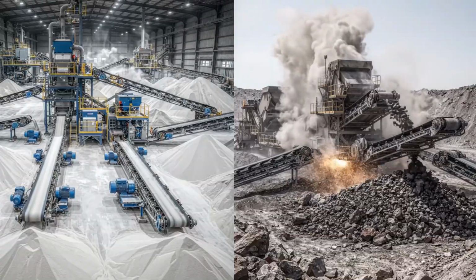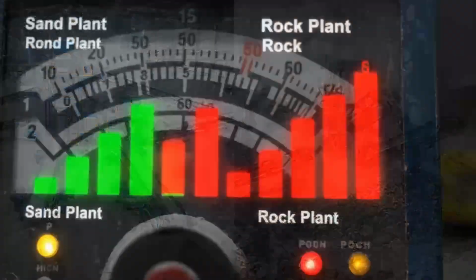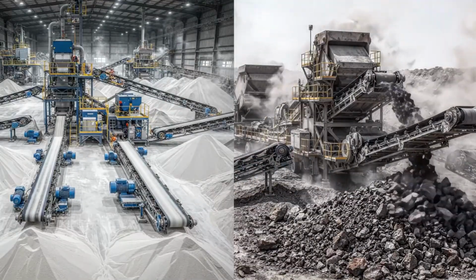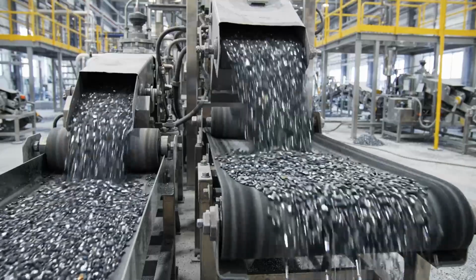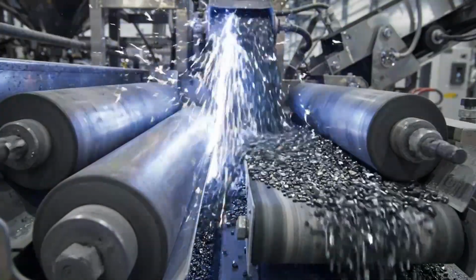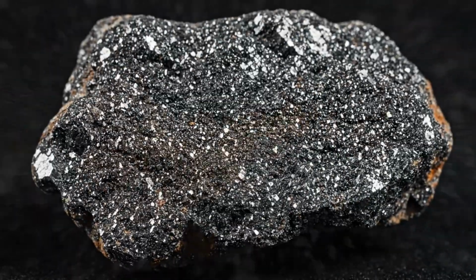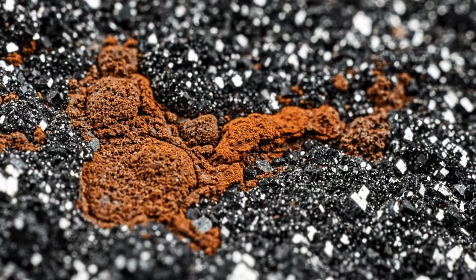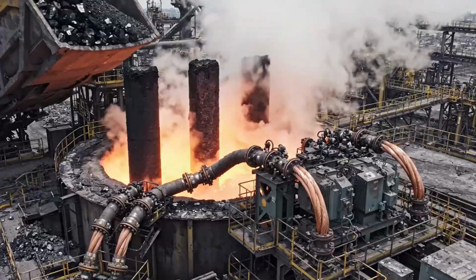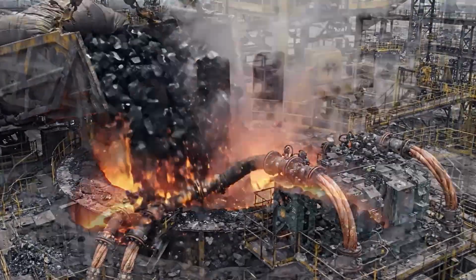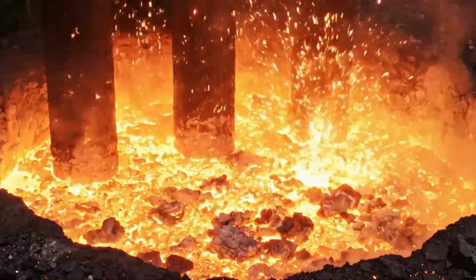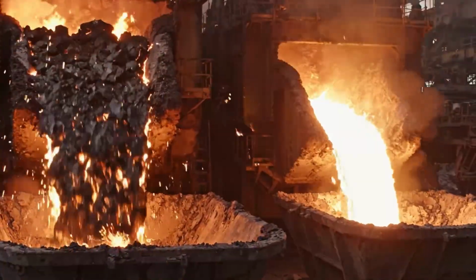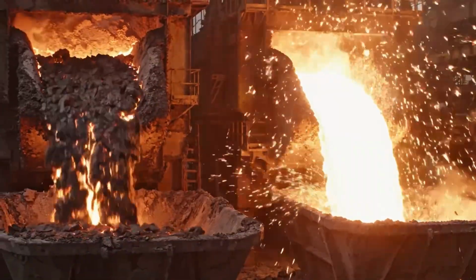Once the concentrate is obtained, the ore is still far from being metal. Ilmenite, for example, contains a lot of iron, and that iron must be removed or reduced before further processing. In some cases, ilmenite is transformed into a richer raw material known as titanium slag or synthetic rutile. To produce titanium slag, ilmenite is fed into high-temperature electric furnaces along with reducing agents. The iron is separated in metallic form or as a different compound, while the titanium is concentrated in a titanium